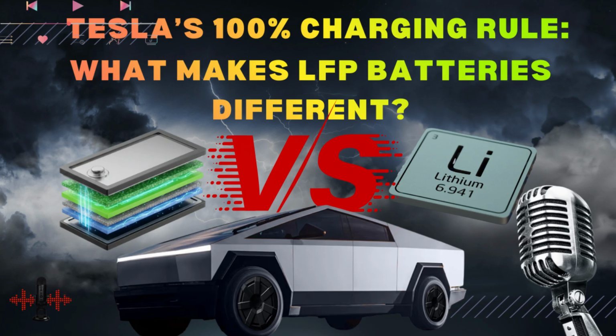So when you stack up these four advantages, minimum capacity loss, near zero replacement risk, slower depreciation, and just total charging freedom, it becomes profoundly clear that Tesla's engineering strategy here was about far more than just saving a few bucks on materials. Yeah, the sources really confirmed this was a targeted choice. The goal was not maximum peak performance. It doesn't offer the highest acceleration or the ultimate maximum range. Those specs still belong to the more volatile NCM chemistry in the performance models. The goal, then, was defined as minimum aging and maximum life.